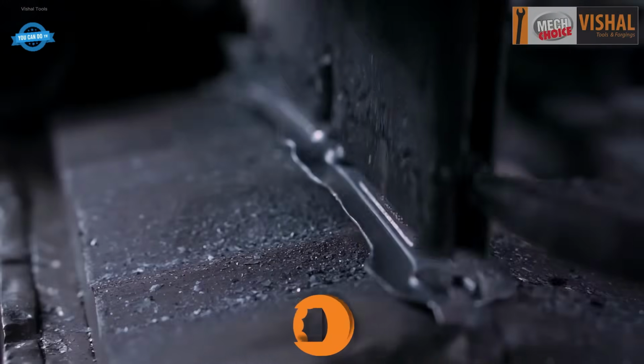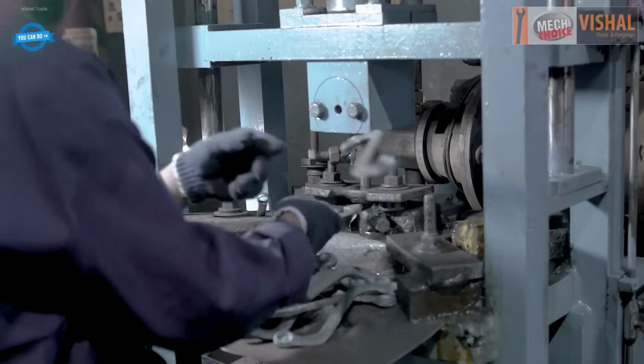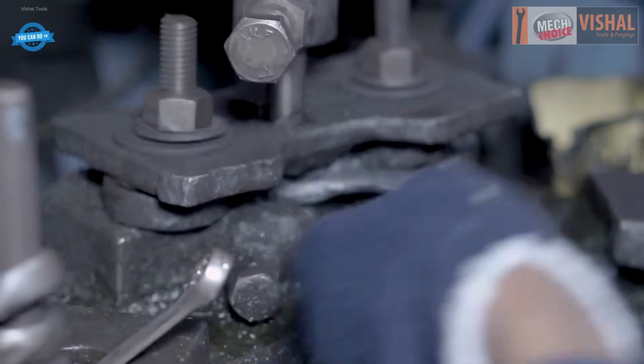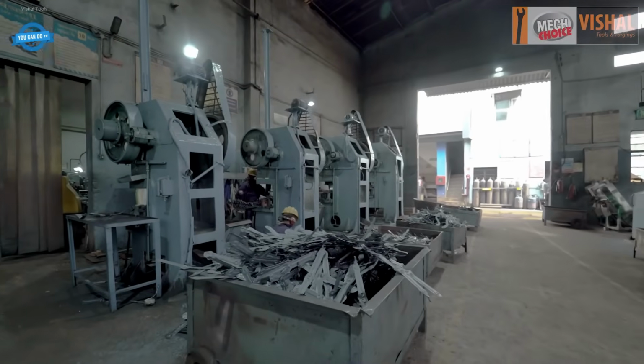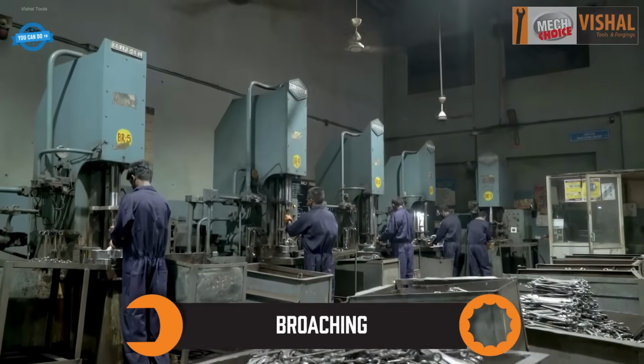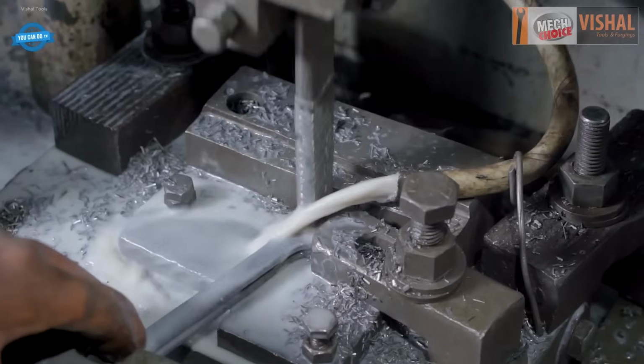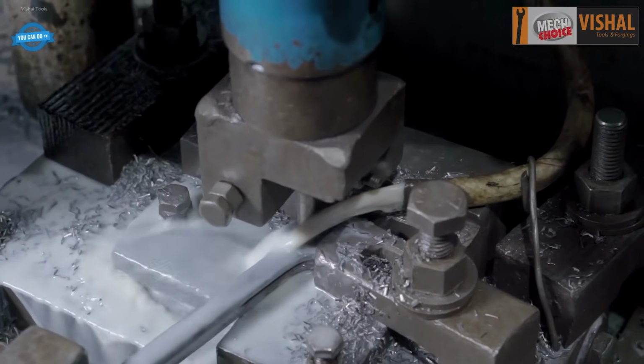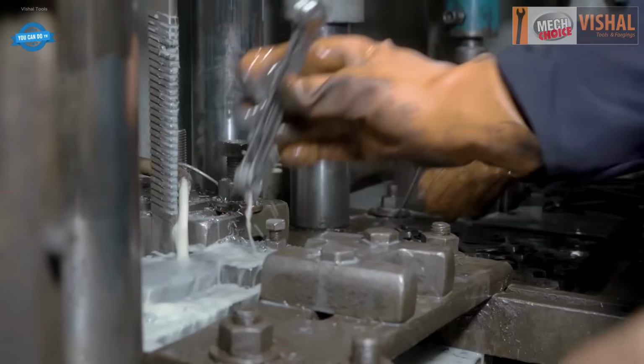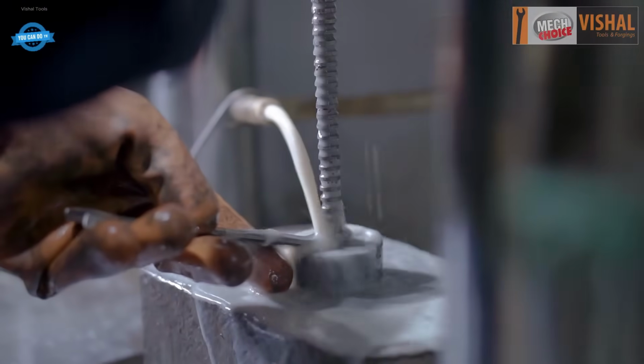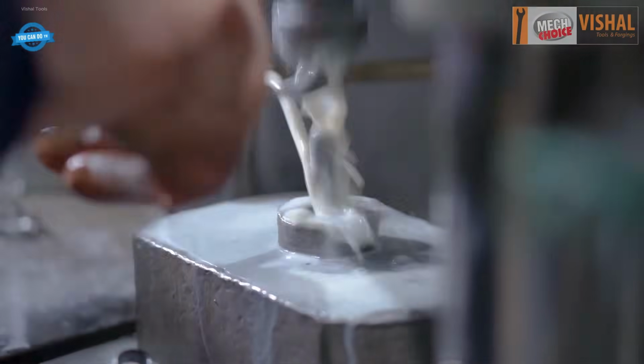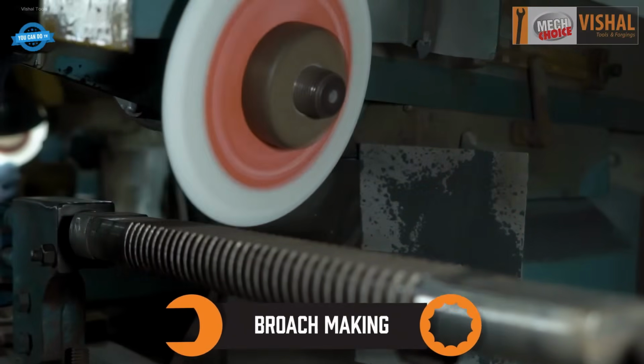Raw materials, specifically chrome vanadium steel, are tested for composition. After approval, long steel flats are cut into blanks using a mechanical press. These are then heated to 1,100 degrees Celsius in a forging furnace and formed into wrench shapes with a drop hammer. Post-forging, excess material is removed via trimming and punching.